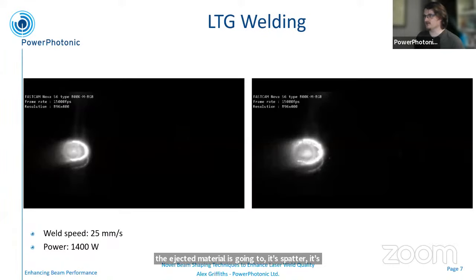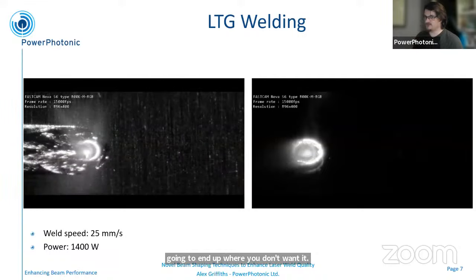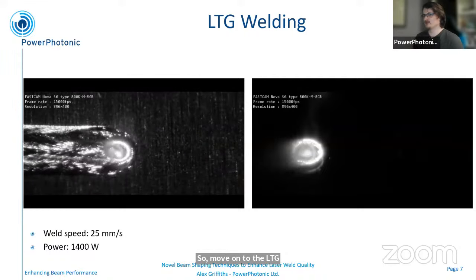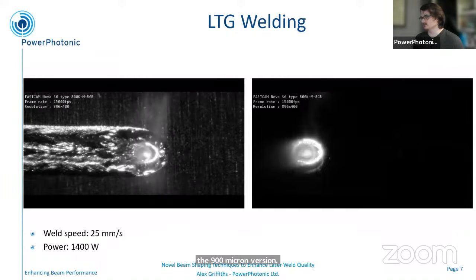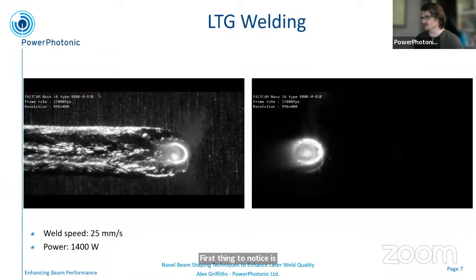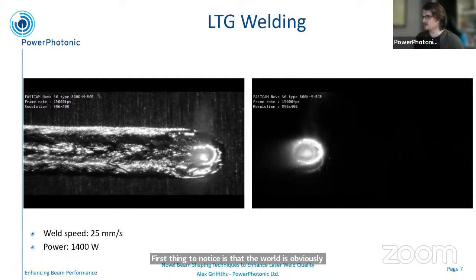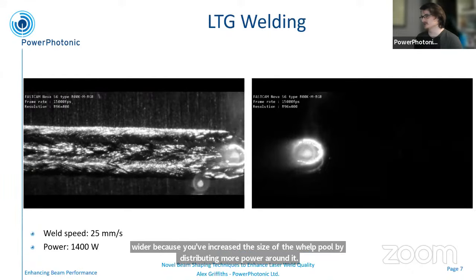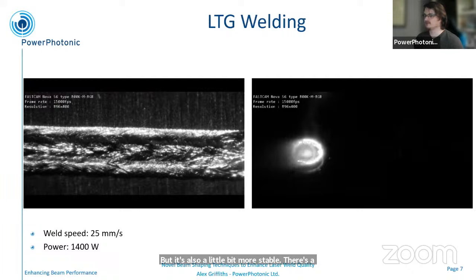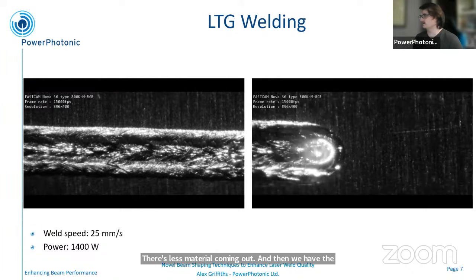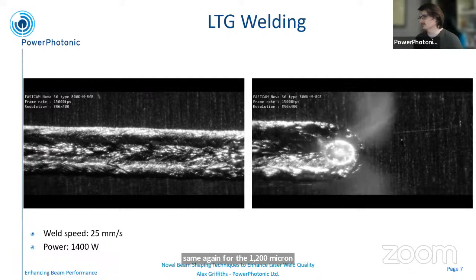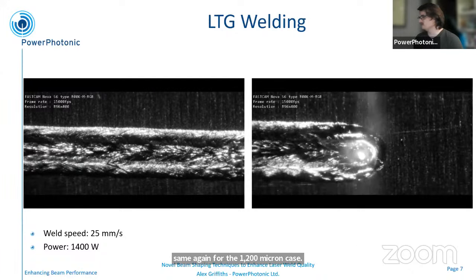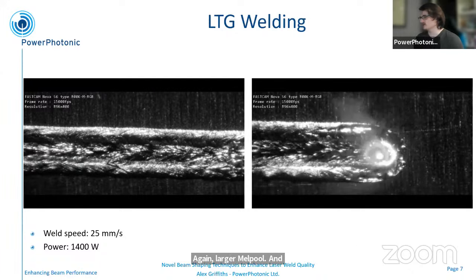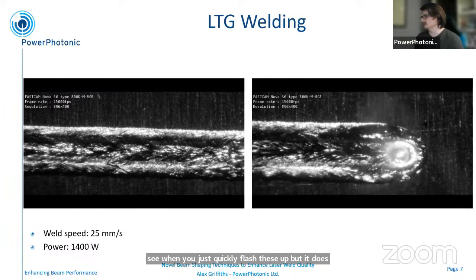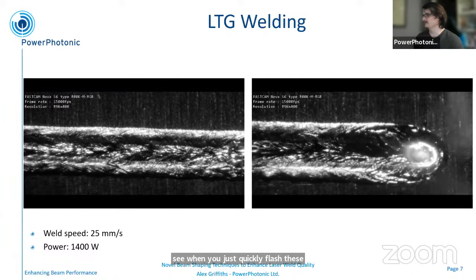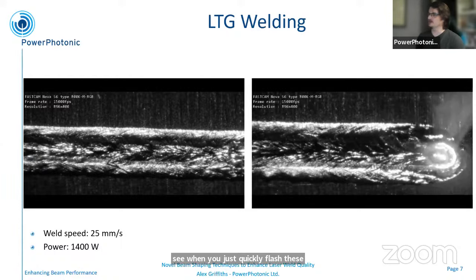So if we move on to the LTG results, on the left, this is the 900 micron version. First thing to note is that the weld is obviously wider because you've increased the size of the weld pool by distributing more power around it. But it's also a little bit more stable. There's less motion in there. There's less material coming out. And then we have the same again for the 1200 micron case. Again, larger melt pool. And it still appears difficult to see when you just quickly flash these up, but it does appear a little bit more stable as you increase the diameter of the ring that you're using for the welding.